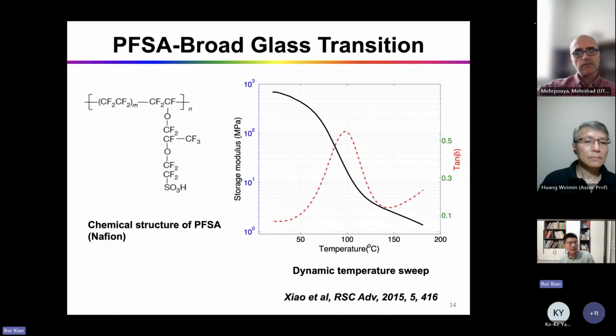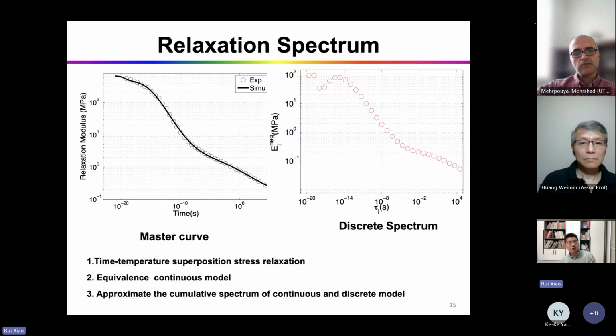Take epoxy, for example—it's a very broad glass transition material. You have these materials with glass transition ranges. We can do some tests called time-temperature superposition, and we can get a master curve for the relaxation modulus, then we can get the parameters for the model.